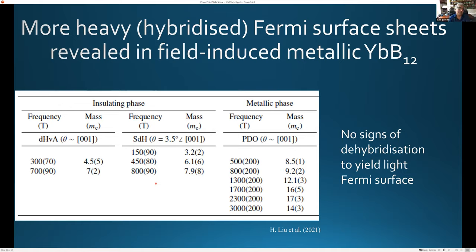And then when you go to the metal, you have a metal-insulator transition, and you're mixing in conduction band modes, and even the F electrons are becoming actual electrons rather than being spinons. So yes, I see what you mean. So the heaviness would be more consistent with F electrons? Yeah, it is reasonable that in this case it seems like these have more of the F electron character, as opposed to, say, samarium hexaboride, which had very light masses and seemed to have more conduction. Right, okay, that was kind of my point.